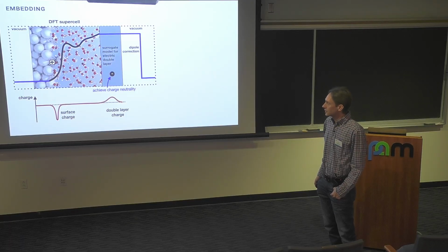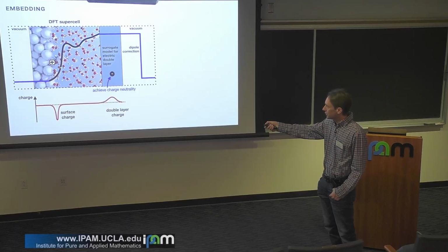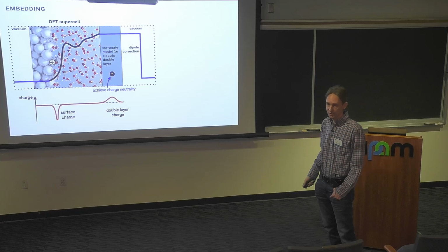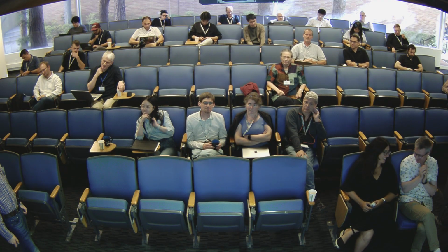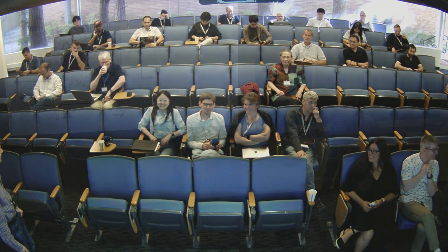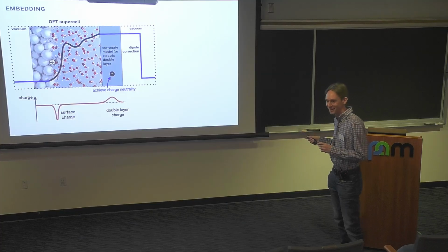Yeah, we tend to divide that into different parts. So the first directly adsorbed layer would be the inner Helmholtz layer. Then we have some solvated ions. That would be the outer Helmholtz layer. And then after that, we have the diffuse layer, where we still have an excess of one particular ion species. And at what level of theory and simulation are you treating this surrogate model layer? I come to that. That's the point of the talk, how you do that. So it's just about the setup for the moment.